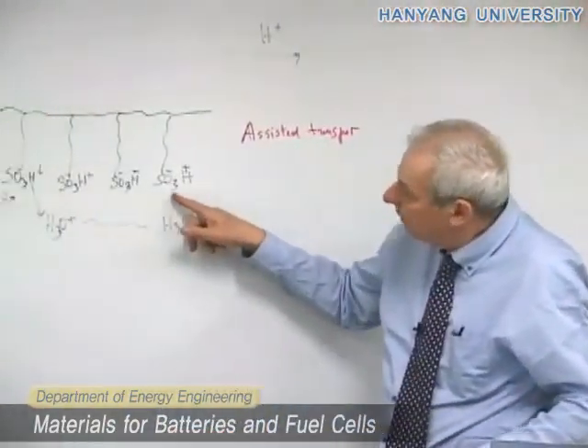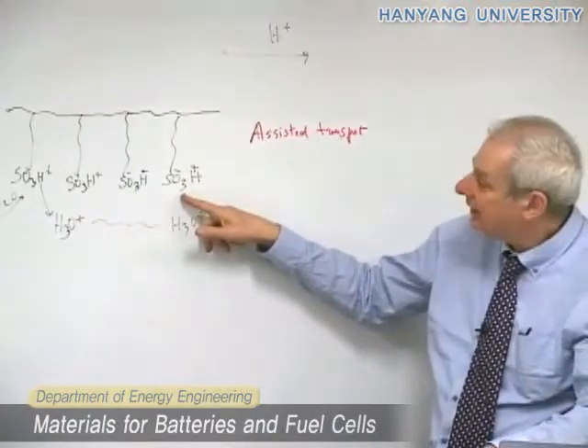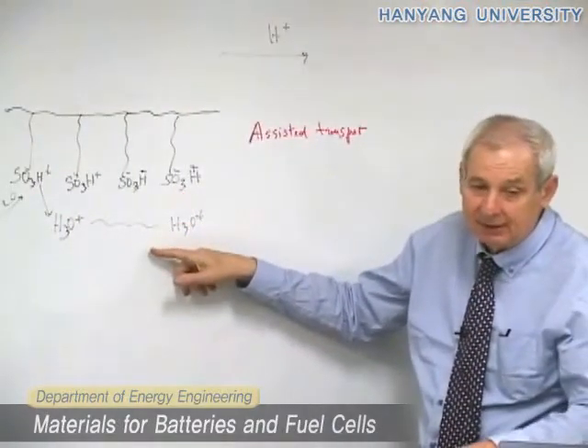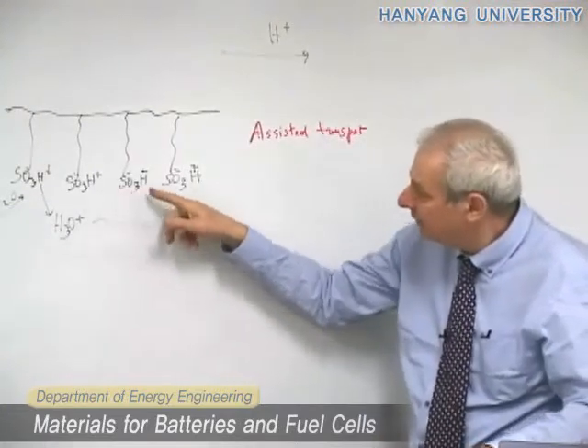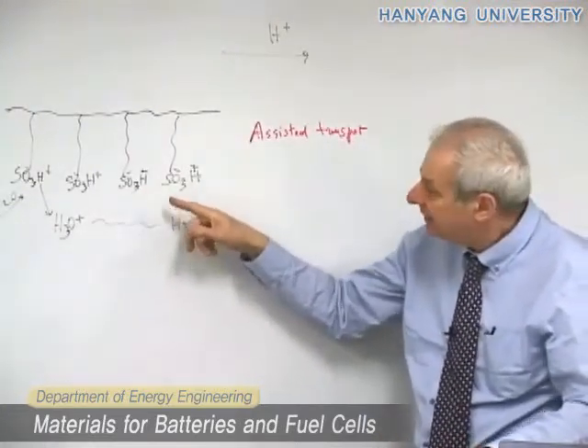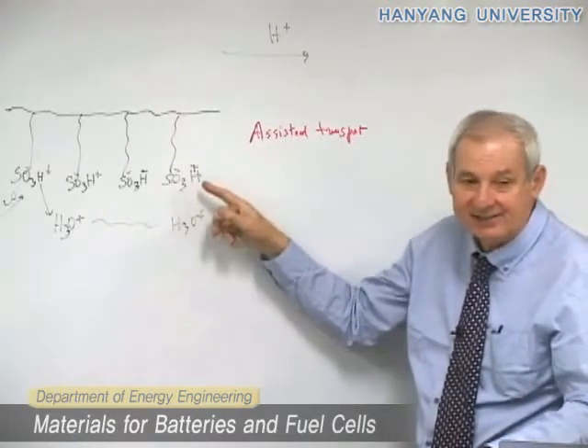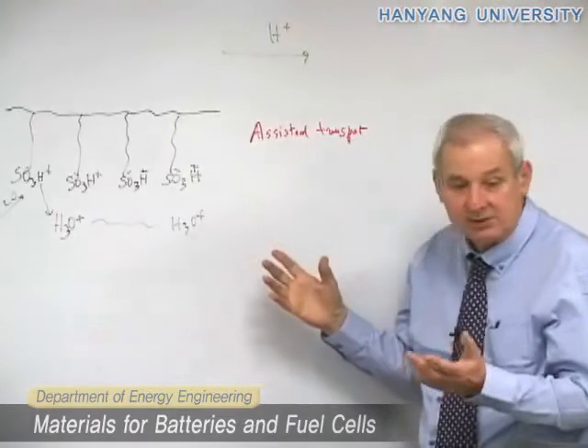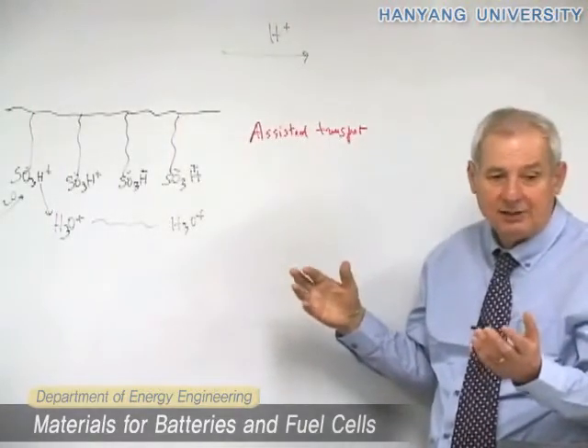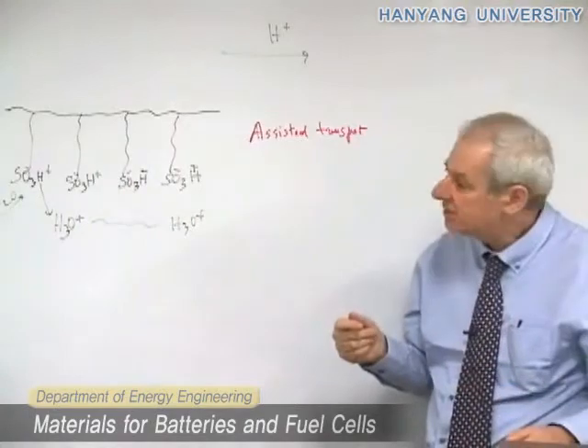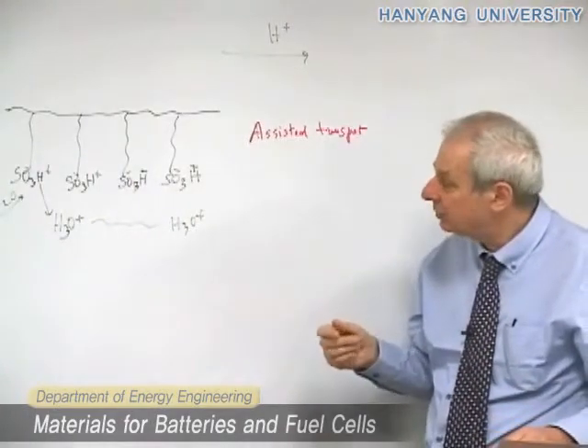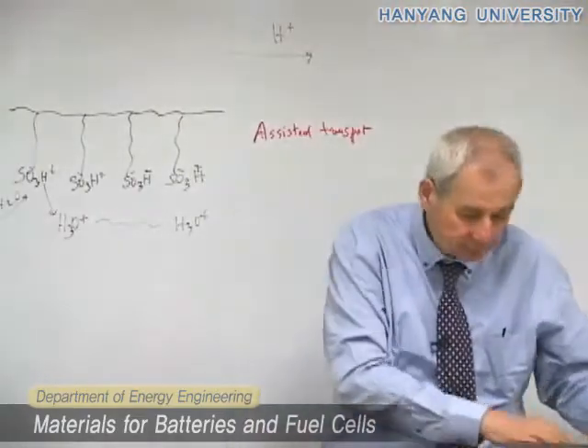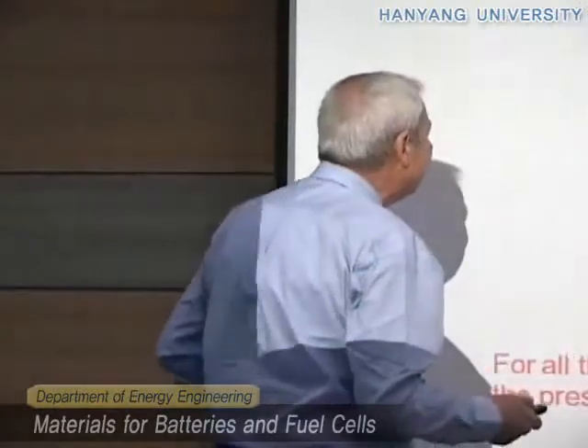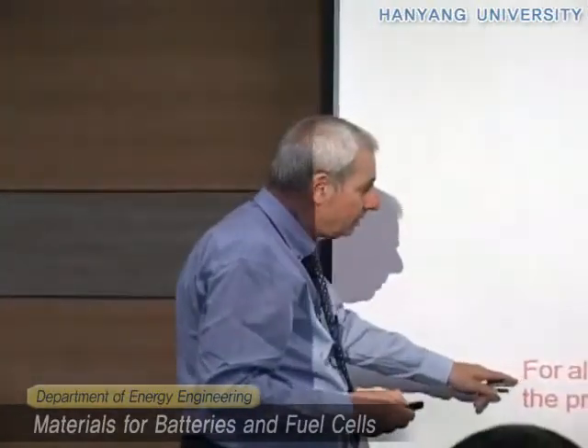if you have 4 groups like this and 4 molecules of water, it's already a little bit too much because you are involved in all the groups, but it's still okay. But if the number of water molecules is 6, 7, 8, then the excess is not useful for the conductivity. And you have the membrane which is full of water. And it's not good for the operation. So the water content is very important here. So for all these membranes, the proton conductivity relies on the presence of water.